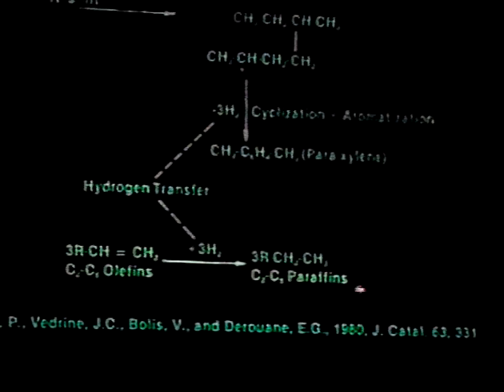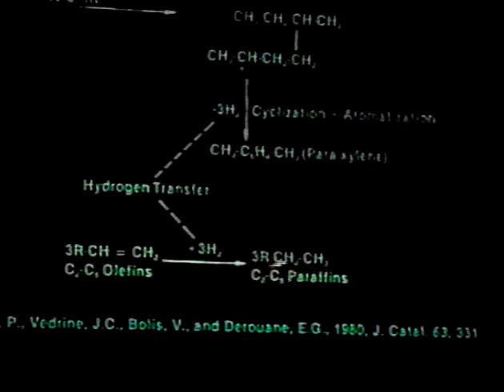They get hydrogenated to give you the light paraffins. That is the reason why when you find a large fraction of aromatics in the product, you also find a relatively large fraction of light alkanes in the product. Our next postulate was that these light alkanes undergo hydrogenolysis on the cobalt, in spite of the fact that there is a considerable amount of CO around, and give you additional methane.